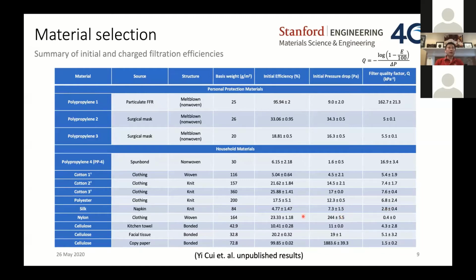Nylon one, this one is woven structure, and its air pressure drop is too high, 240. Filtration efficiency is reasonable, 23, but its quality factor is low, it's 0.4. It's too low, this type of nylon. Now let's look at cellulose. This is the paper I referred to. Even kitchen towel has quality factor of 4.